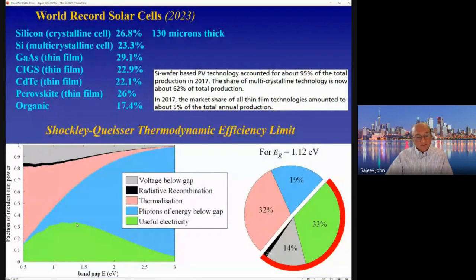So there's a trade-off between these two effects, and that is defined by this green curve. And the maximum occurs in the case of semiconductors with a band gap between 1 and 1.5 electron volts, and both silicon and gallium arsenide fall in that range. If we look more specifically at silicon with this band gap of 1.12 electron volts, then in fact 32% of the energy from the sun just is thermalized by the relaxation of carriers down to the conduction band edge. 19% of the sunlight falls below the band gap, and can't be absorbed.